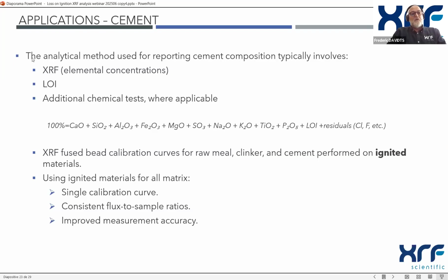Now another application, the cement. Again, the analytical method used to report cement composition involves XRF analysis, so elemental concentration, loss of ignition, and also additional chemical tests where applicable, and surely for some elements like chlorine, fluorine, etc. But nevertheless, the loss of ignition is part of the whole to get 100% of the cement. So it's common in the cement industry to prepare the calibration curves for the raw mill, the clinker, and cement. We work with the ignited materials because we can work with a single calibration curve. We have a better consistent flux to sample ratio, and clearly using that, we have a better accuracy.